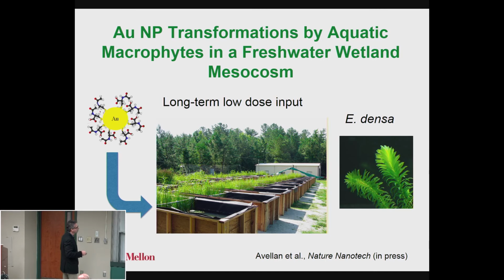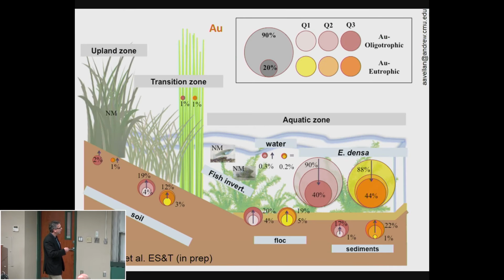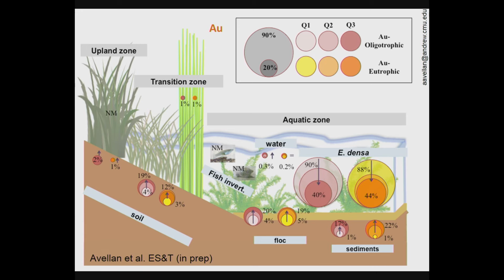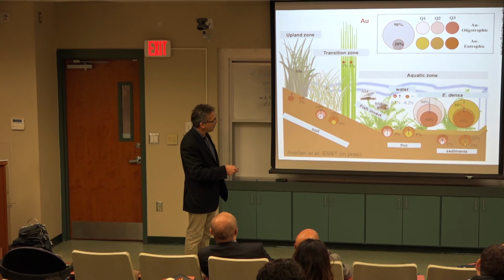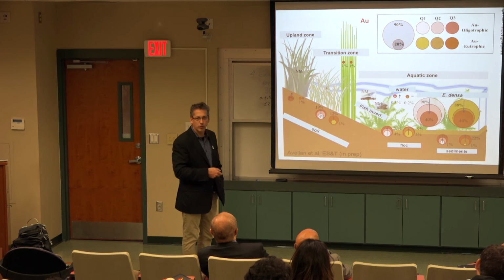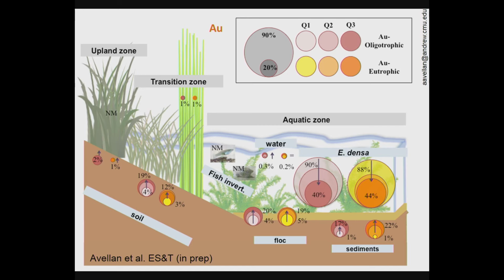Okay, so we put them in these things with very low doses, like microgram per liter kind of numbers, every week for 9 months, and we looked at these Egeria plants and we collected them up. And then we figured, okay, there's going to be some gold with Egeria. It turns out this is a very busy thing and it hasn't been published yet, but 88% of the gold that we put in actually was associated with these plants. So the plants were taking up most of the gold that we were putting in the system because they were filtering the particles. That's what they do. They help keep the water clear. Okay? So most of the gold was present with those plants.